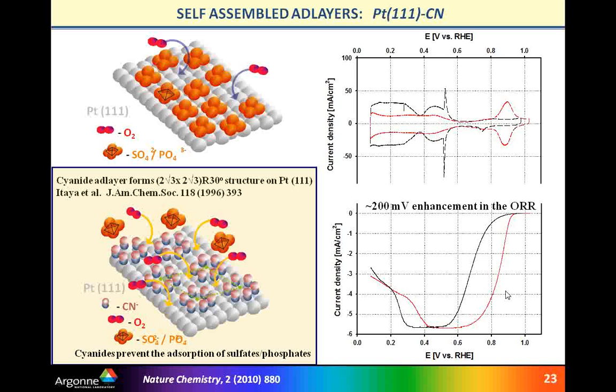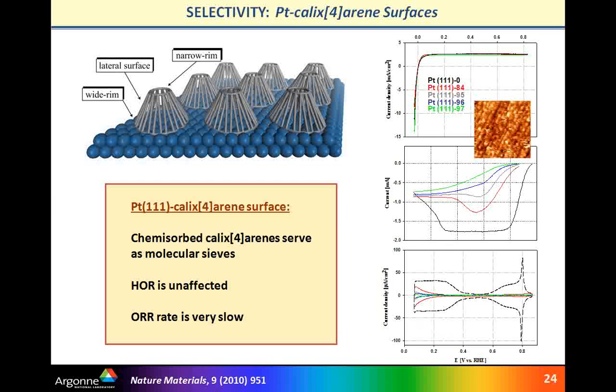The second example is more about stability. It is very well known that due to the start-stop conditions and due to the undesirable oxygen reduction reaction on the anode side, there are problems with the potential at the cathode side, go to very positive potential, and then the electrode is becoming very unstable. We managed somehow, our goal was somehow to modify platinum surfaces in such way that, again, it would be selective, but in this particular case just for hydrogen and to reject oxygen. Certainly, this is much more actually a tough thing to do, simply because oxygen is also rather small.